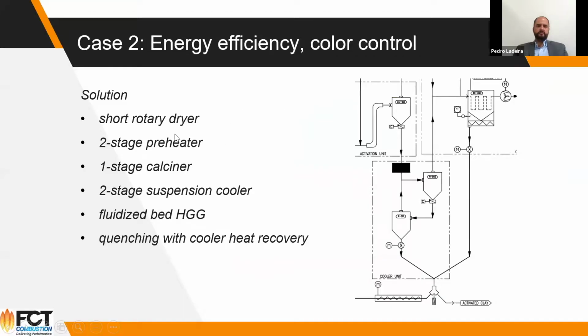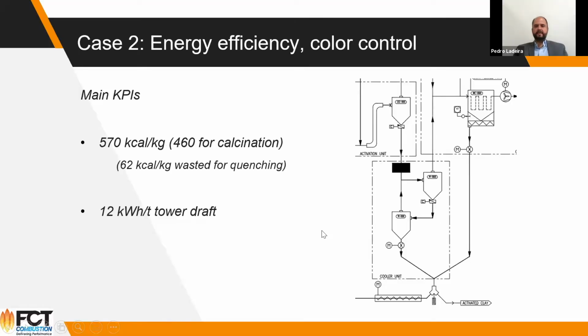So the solution is this: a rotary dryer, 2-stage preheater, 1-stage calciner, 2-stage suspension cooler, a fluidized bed, and a quenching with cooler heat recovery. So we want to control color here in this case. And the main KPI here is you're going to have 570 kilocal per kilo, 460 only for calcination. Some of the heat is wasted for quenching down and keeping the color control running. And you're going to have this 12 kilowatt hour per ton draft. So these are the key factors for this case.